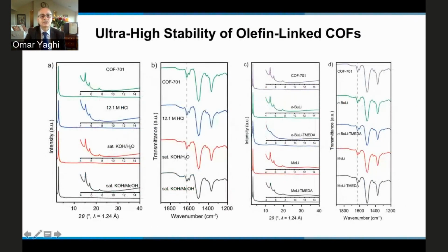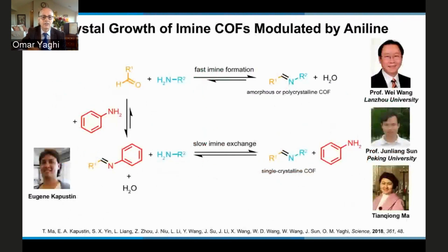Notice the stability of this structure. This is the original COF-701 X-ray powder diffraction. This is the material in 12 molar HCl. This is the material in saturated KOH in water. This is the material with n-butyllithium, methyllithium. So it's a very robust structure. And this is very important for water harvesting or for carbon capture properties, in making robust materials that can work year after year after year without having to be replenished or regenerated in terms of their structure.